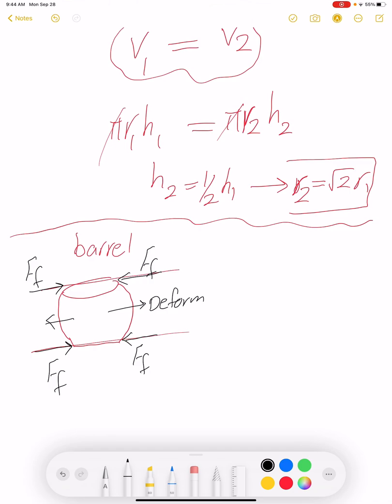So at the end we are going to have a barrel shape. If we are going to remove the effect of friction or minimize it, we could use lubrication. We could add lubrication to these regions and then we are going to see a much closer shape to a cylinder.